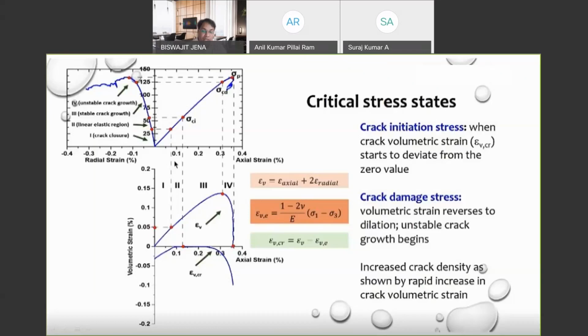The other important point is the crack damage stress, where the volumetric strain reverses to dilation or failure. So you see that point marked 4 in the curve, where the volumetric strain starts to go back into dilation, and then the crack damage stress. Volumetric strain reverses to dilation, and you have an unstable crack growth that is happening. So that is the crack damage stress, and we will call the crack initiation stress and the crack damage stress the critical stress states for ultra high performance concrete.